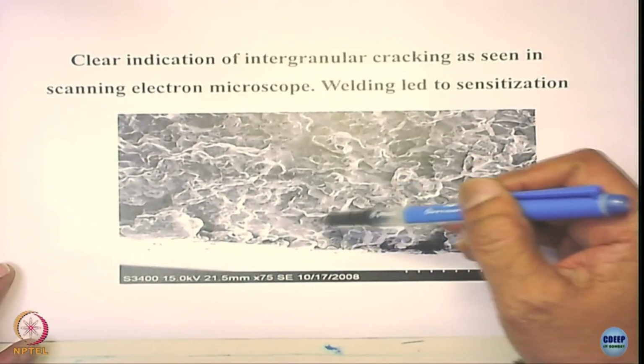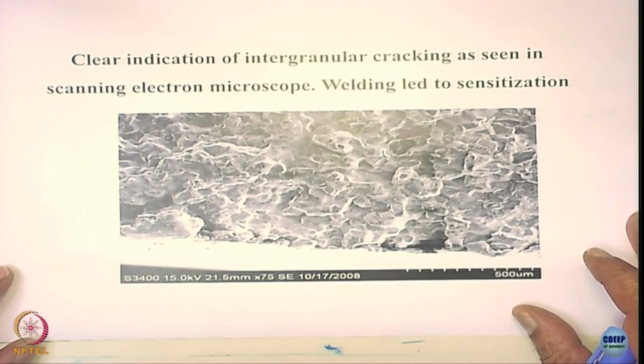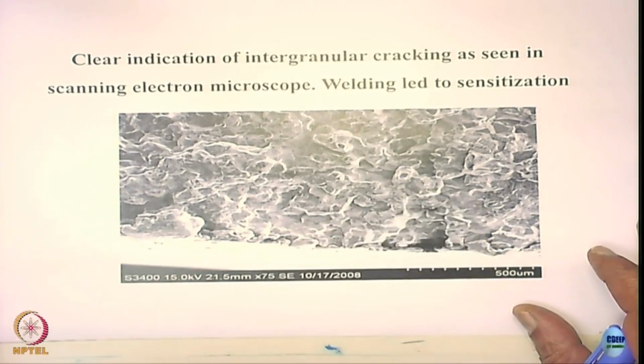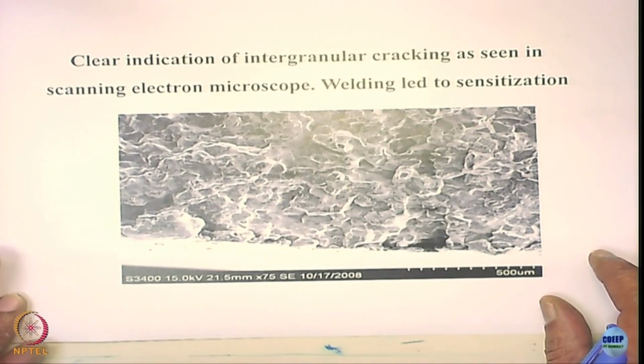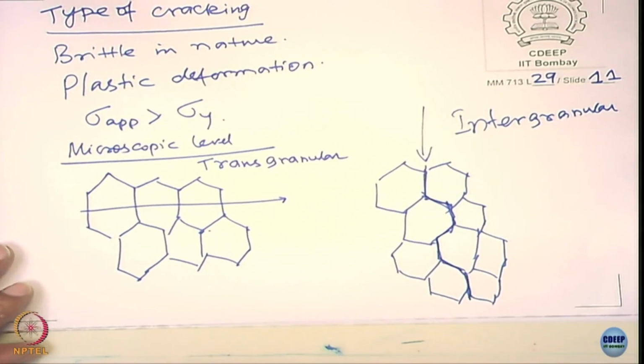The corrosion has occurred selectively along the grain boundary and the crack starts moving along the grain boundary. So the grain boundaries are relatively electrochemically active. I use the term electrochemically active because it can be anodic, or sometimes cathodic, which happens in the hydrogen embrittlement case. But if the preferential dissolution takes place here, and the grains are not deformed, you see a huge amount of intergranular cracking taking place. This is one way of looking at it. There are cases where it is not necessarily 100% intergranular or 100% transgranular, it could be a mixed kind of failure. So this is what really happens.